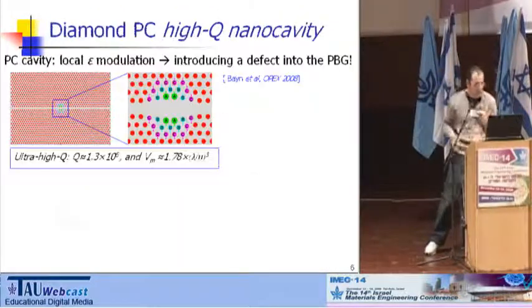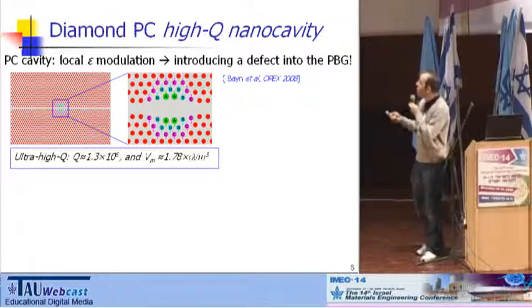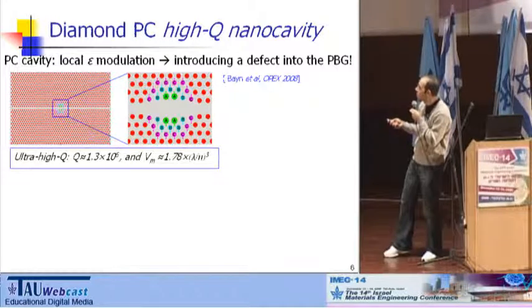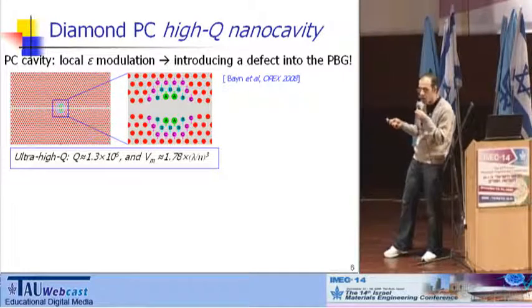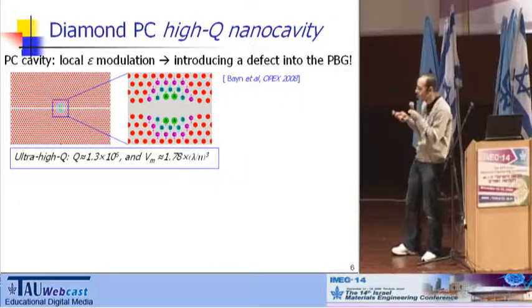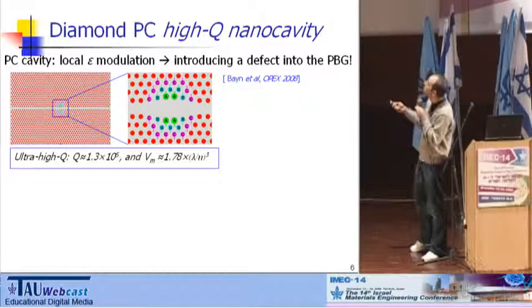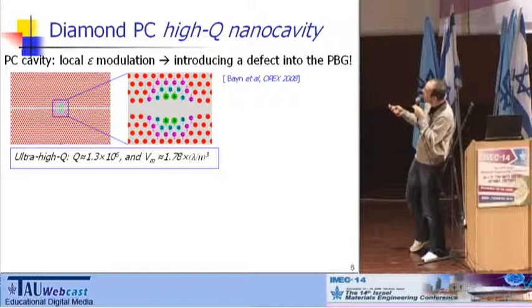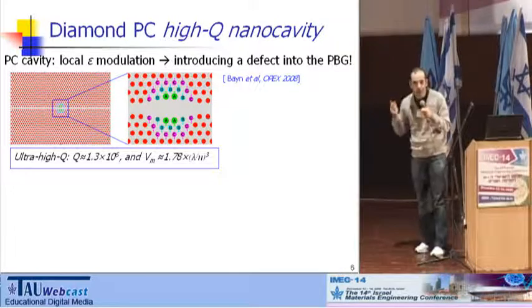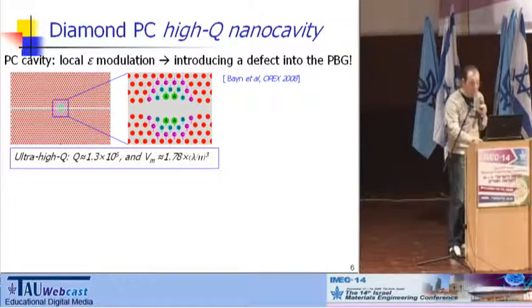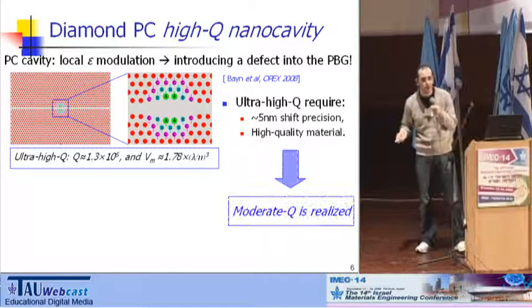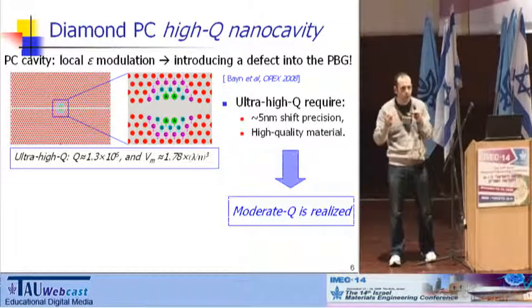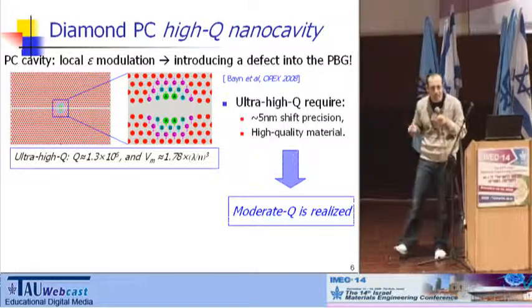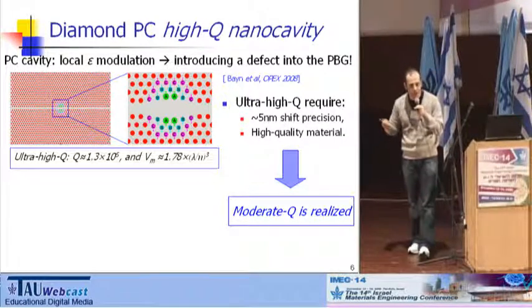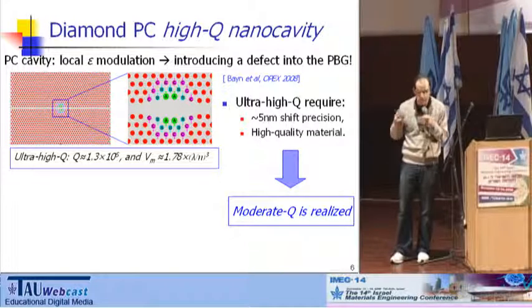So, in our group, we have derived the cavity design, which produces a theoretically ultra-high Q nanocavity with the quality factor over a million. To fabricate this cavity, we have to move the holes outside of the linear defect, which is actually a photonic crystal waveguide. The hole shift precision must be around 5 nanometers, and also we must work with very high quality material.